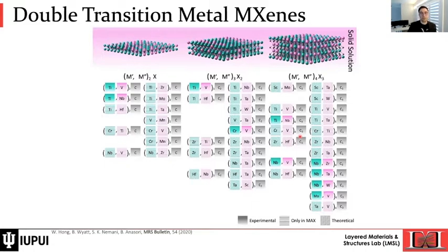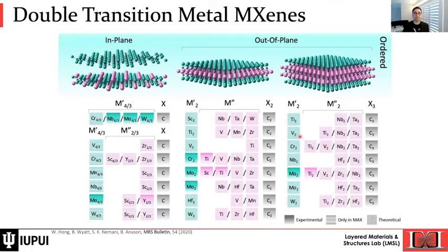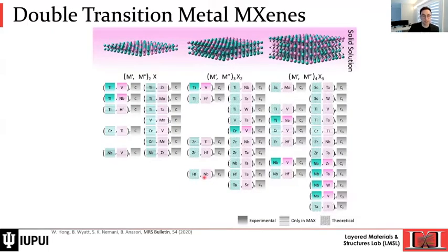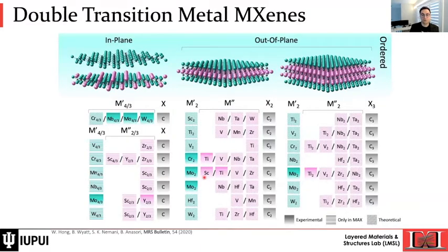Also, a unique feature of the MXene family is that when we mix certain transition metals, such as molybdenum and titanium, or molybdenum and scandium, instead of forming a solid solution that I just showed in the previous slide, they will prefer to have an ordered structure. So without doing any growth or bottom-up synthesis, we can design these atomic sandwiches, layers of transition metals forming ordered structures with carbon between them and covered with surface termination. So we have a really high level of control over composition, structure, and ordering of the atoms in MXene structures.